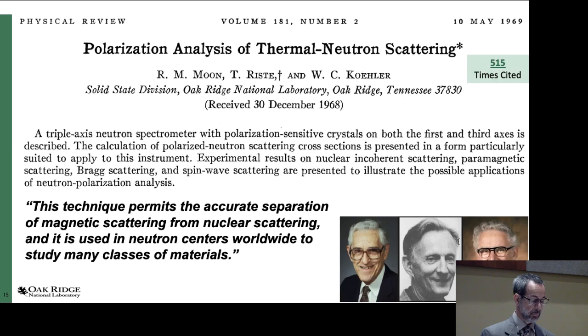But one of the papers I'd like to showcase here is the polarization analysis of thermal neutron scattering that Ralph Moon, Tormod Riste, and Wally Koehler developed. This was using a triple axis spectrometer in an elastic mode. And this technique permits the accurate separation of magnetic scattering from nuclear scattering. It's widely used all around the world.